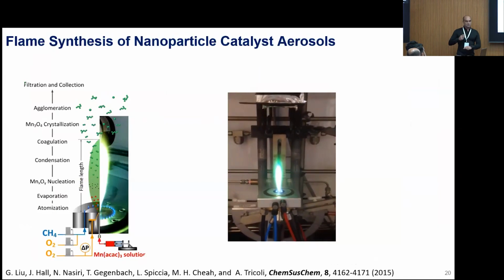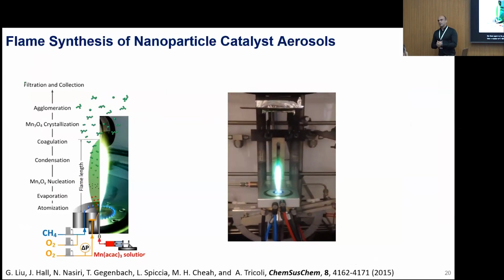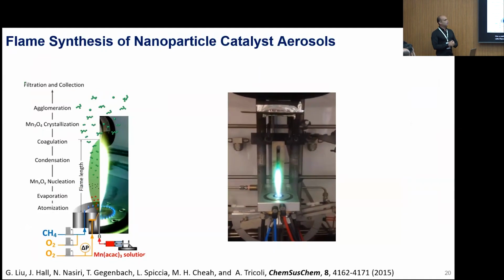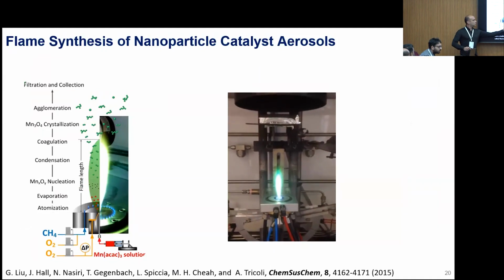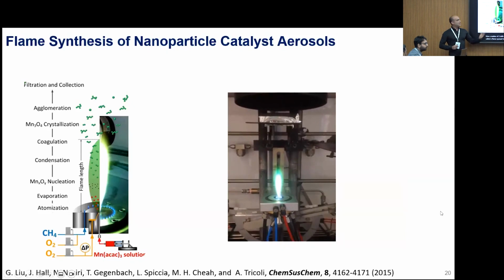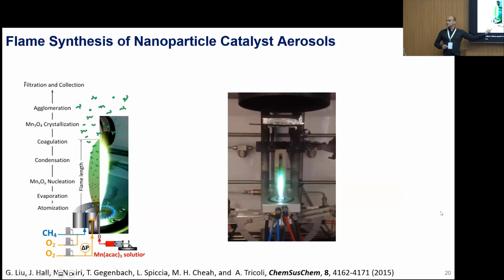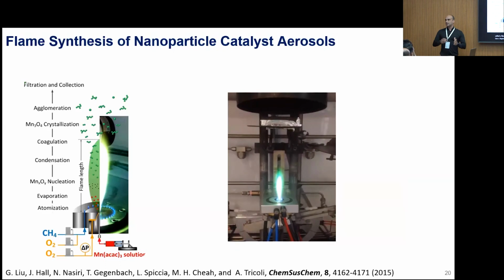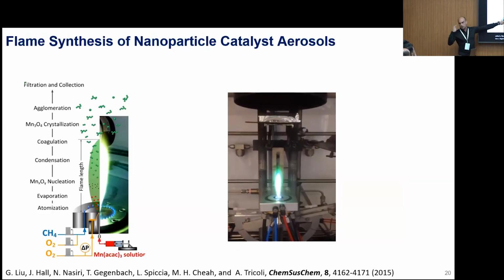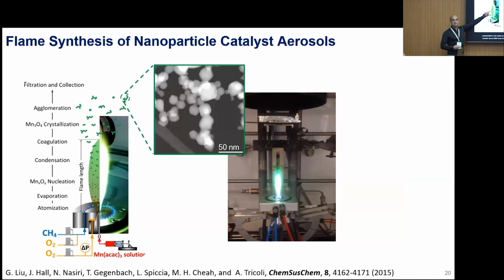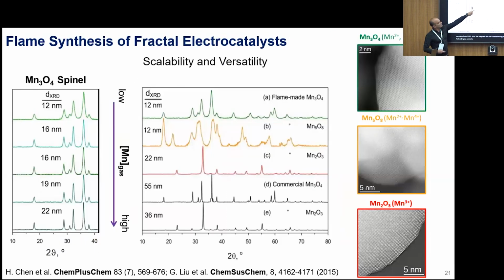And this is the flame in the lab. It's called a flame spray pyrolysis system, which basically enables us to use a liquid solvent, put as many metal salts in it as we want, and then atomize it. That's the noise. This is the atomization, and it makes small droplets that we ignite. And then we have a reactor that runs at about 2,400 degrees, and it can continuously produce in this small space these small nanocrystals. Not only can you produce them, they are highly crystalline, as you can see there, so you don't need post-processing in principle.